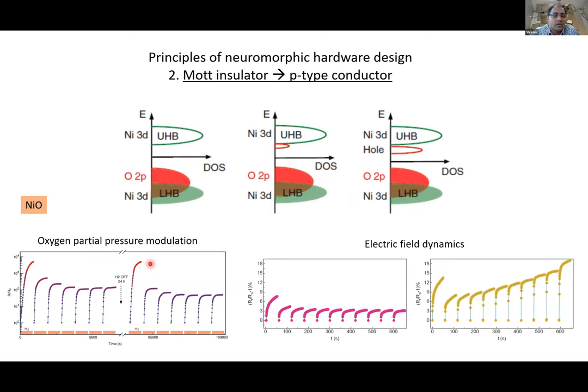So this is one example. This is an experiment done at about 500 Kelvin in a furnace. What we are doing here is taking nickel oxide, a simple thin film on a substrate like sapphire. We expose it to hydrogen gas, and then you change the resistance. So the resistance increases because the material is reducing. You're basically creating more of nickel 2+, which is close to the Mott insulating state.